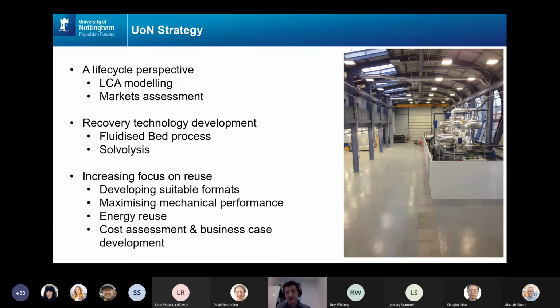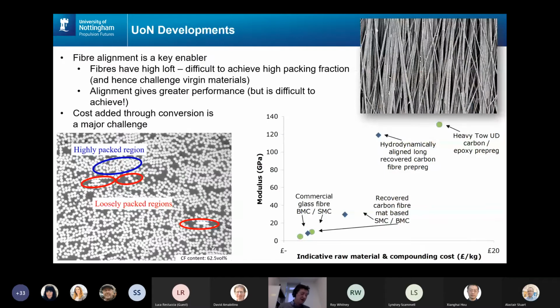And so a lot of the work is scale up, technology readiness assessment, and effectively business case development, looking at energy and automation and how we can make these fibers for a low cost. So the biggest problem with these fluffy fibers is that they have excessive loft, a bit like cotton wool. If you squeeze it, you can't really achieve that high packing fraction of fibers that you want in order to make a high performance